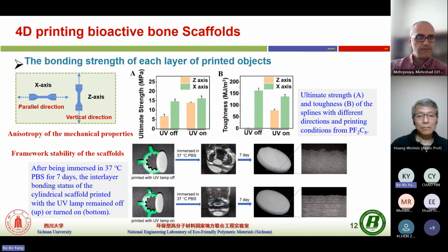We found that the anisotropy of the mechanical property has been modified, especially in the vertical direction, like the printing direction, and the tensile strength has been obviously enhanced. That means the binding strength of each layer has been enhanced.